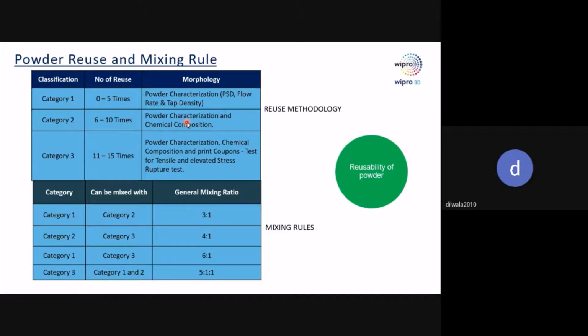The first category, what we call category 1, is where we have used powder from 0 to 5 times. After the 5th reuse, we do powder characterization, which means I do particle size distribution, we do flow rate, and we do tap density to just see whether the powder is within the acceptance limit. Second category, if the powder has been used from 6 to 10 times, after the 10th reuse, we do powder characterization, which means all these tests plus chemical composition.